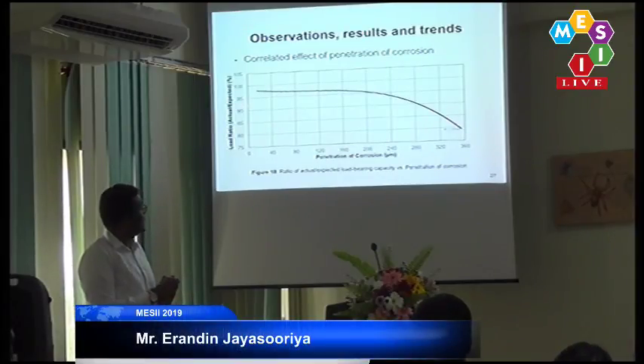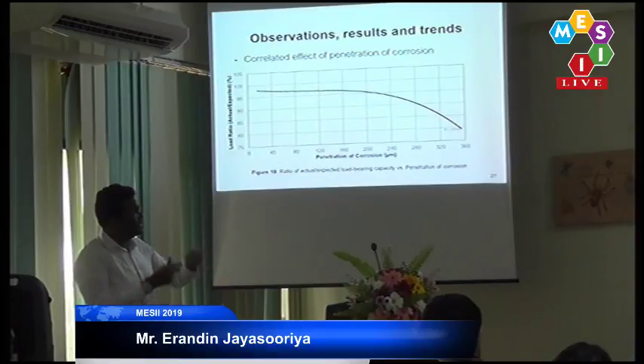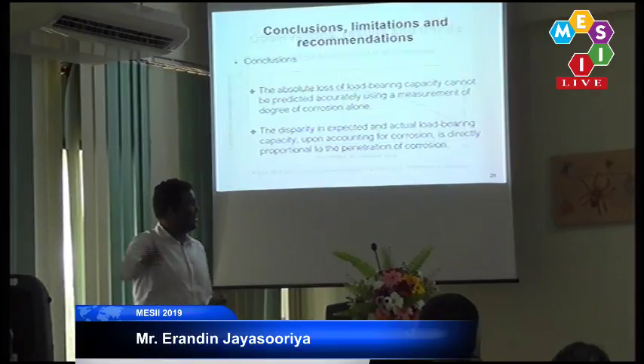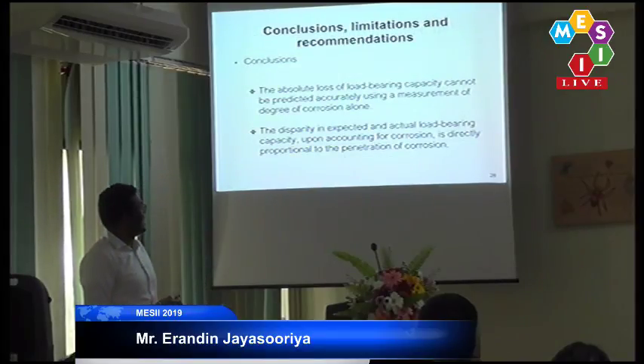But we found out that it wasn't. It deviated quite significantly the further the penetration of corrosion went in. And this penetration kept increasing as well without the general layer following. So that was quite an amazing feat. I have removed the data points because that third anomaly comes somewhere here and makes the graph rather ungainly. But yeah, these are the conclusions I reached.